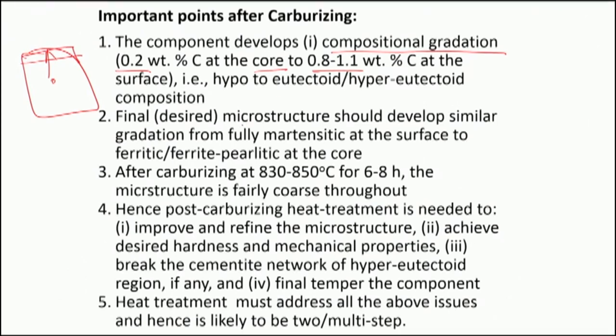We also desire a gradation of microstructure because we want fully martensitic on the top surface and fine pearlitic at the core, so that we actually maintain very high toughness at the core and very high wear resistance at the surface. Both compositional gradation and microstructural gradation are desired.